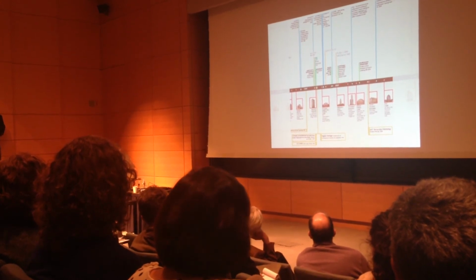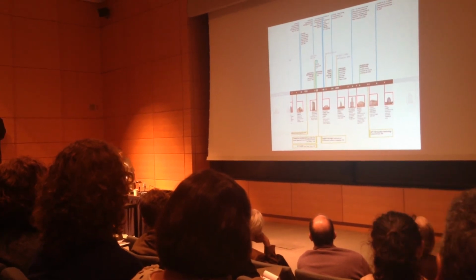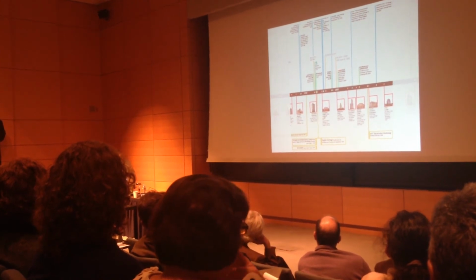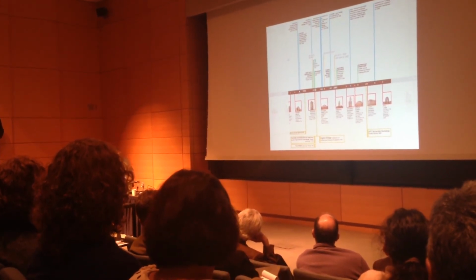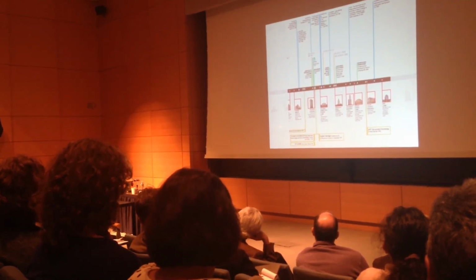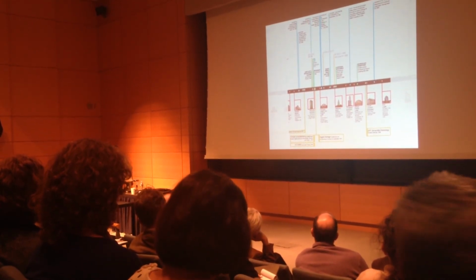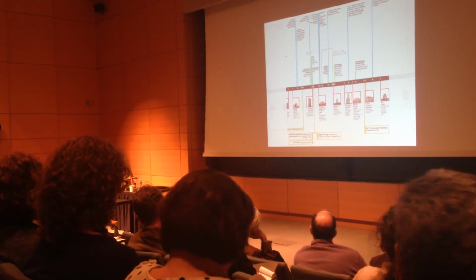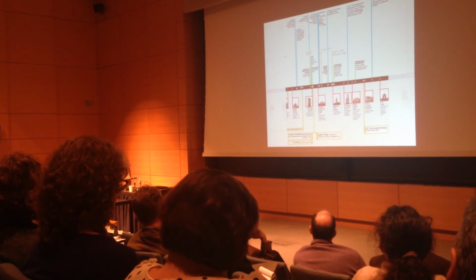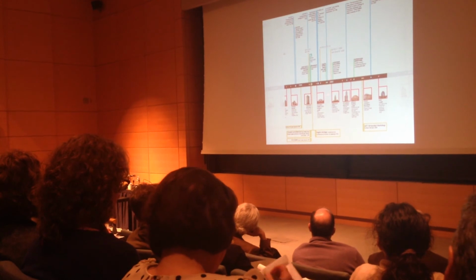So we arrive in 2000, where Prosoco, to remain in the business, to remain competitive, introduces the first product based on ammonium bifluoride, EnviroClean. Ammonium bifluoride is a salt that, dissolved in water, becomes HF. So it apparently has a lower concentration, but because it depends on water and also on environmental conditions such as temperature, it's really not easy to predict the final concentration of the product itself.